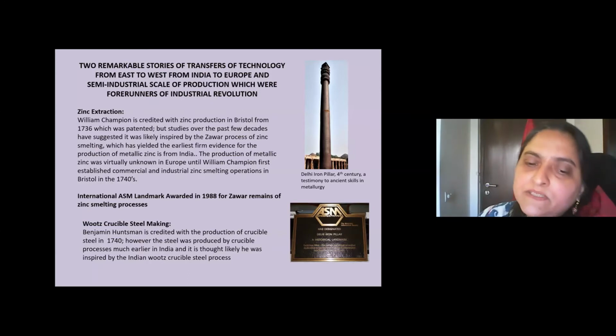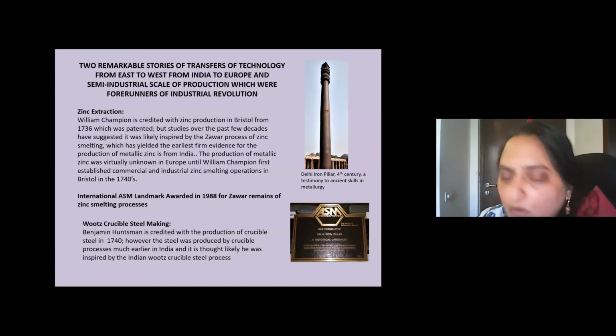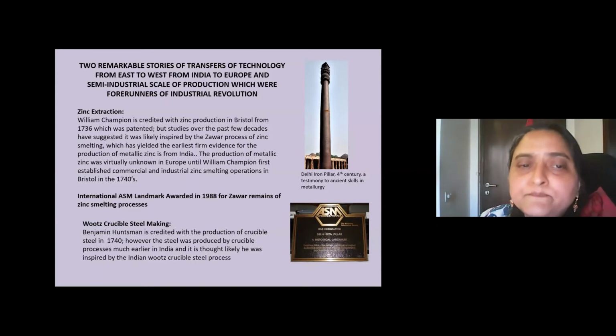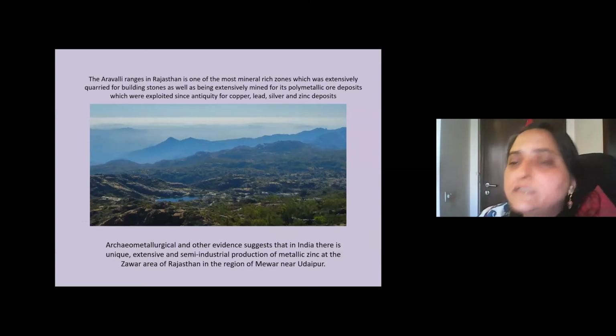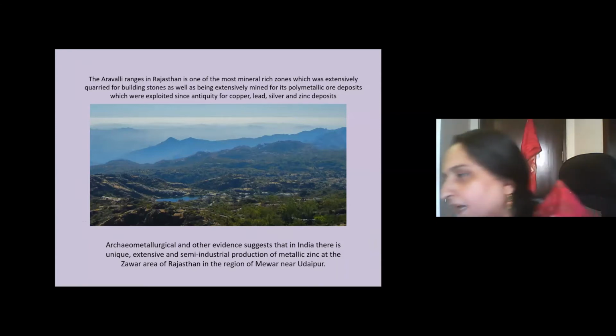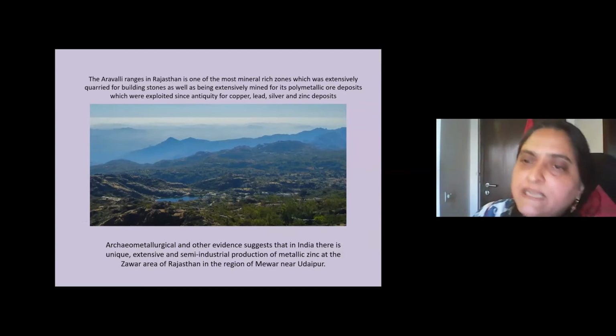Now, Benjamin Huntsman is credited with the production of crucible steel in 1740. However, as I will point out, crucible processes were prevalent in India already for steel making, and it's thought likely now that he was inspired by the Indian wootz steel crucible process. Now, the Aravalli ranges in Rajasthan are one of the most mineral-rich zones, which were extensively quarried for building stones and also mined quite extensively since antiquity for copper, lead, silver, and zinc deposits, because these are polymetallic deposits. And there is unique and extensive evidence for semi-industrial production of metallic zinc in the Zawar area of Rajasthan in the region of Mewar near Udaipur.